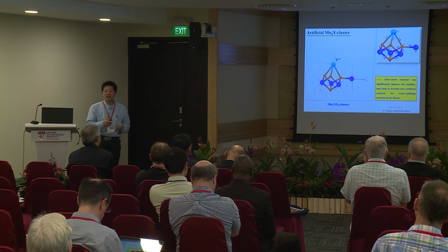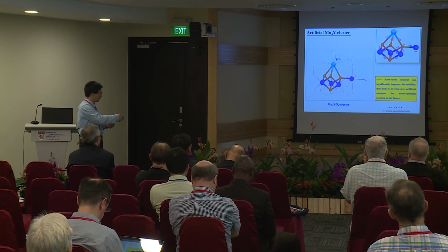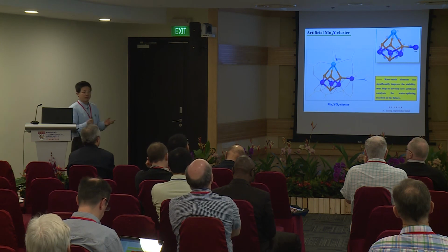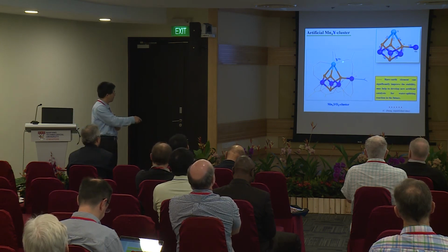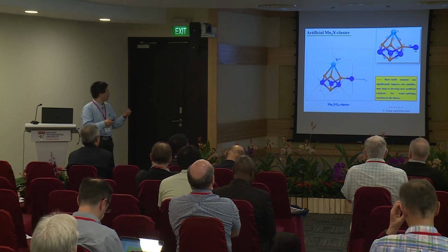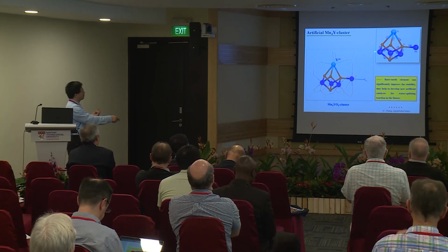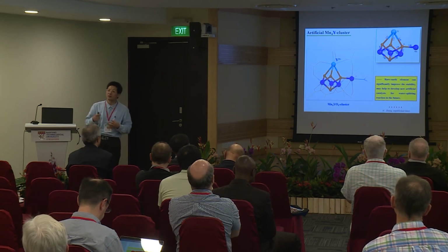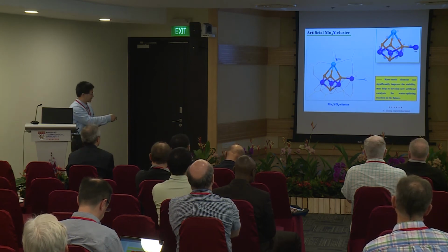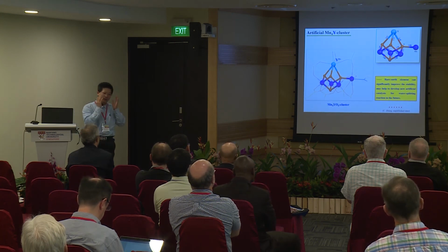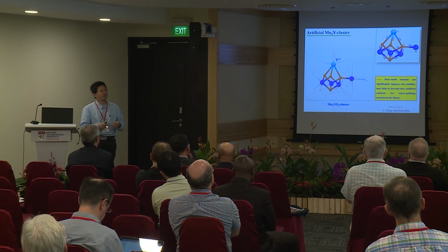Here, you see the structure with yttrium. So here we replace the calcium with yttrium. Yttrium is 3+, with 3 charges. But it's so surprising: the basic structure is just the same as with calcium. All the distances, all the 4 manganese, are just the same as the previous calcium sample. But this model complex is much more stable than the calcium one. It can go to electrochemistry. It is active, but of course we need to work more.